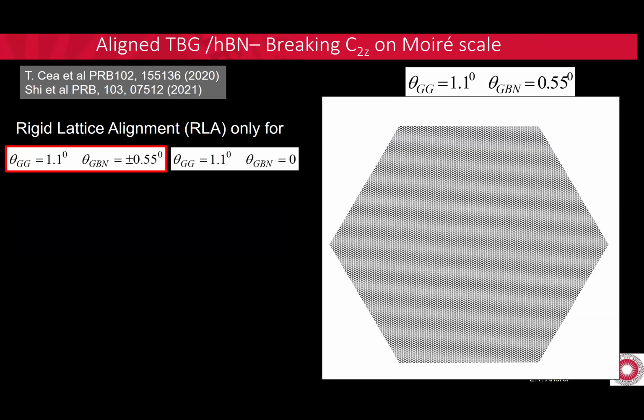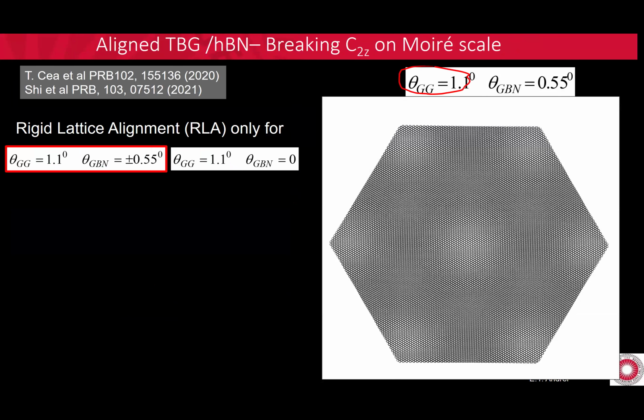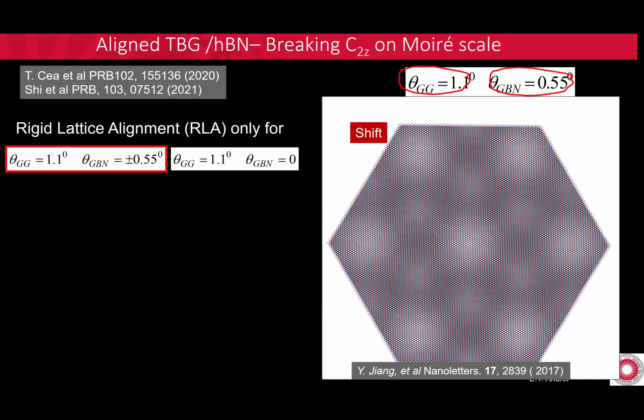Now here's the issue with the shift. Here is my first graphene layer. I'm bringing in my second, rotated to 1.1 degrees, and this is to scale. So this is my Moire, and I hope you can see it. I'm bringing in my boron nitride and rotating to 0.55 degrees. You see, you have a beautiful superlattice. Now, as an experimentalist, I can't really align my atoms, so it can be shifted by a little bit. The problem is, you shift it by 1 atomic space and the change is of the order of the Moire. There is a huge magnifying factor, so hitting it exactly at those angles is practically impossible.